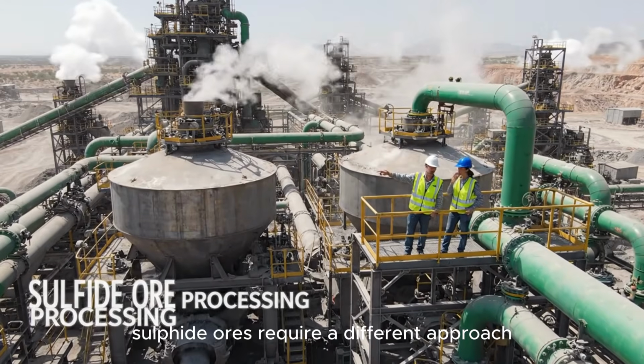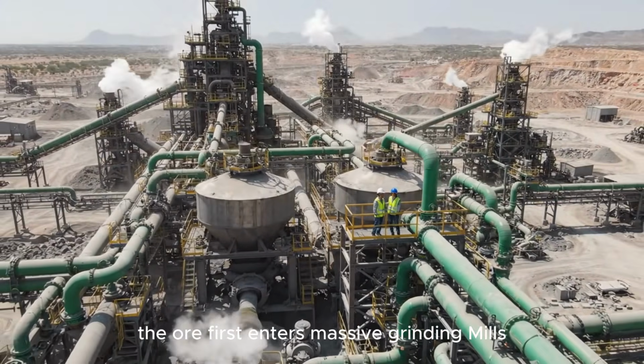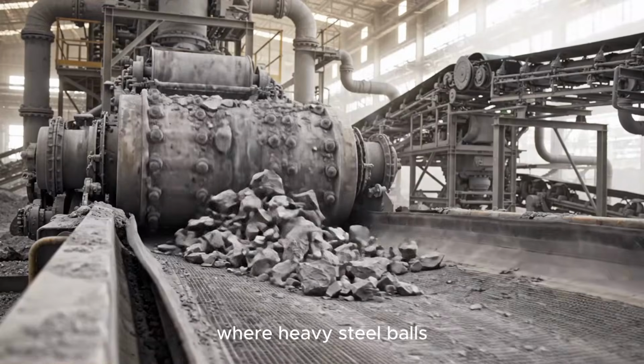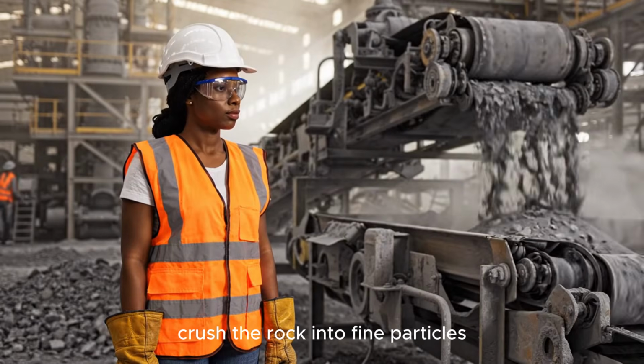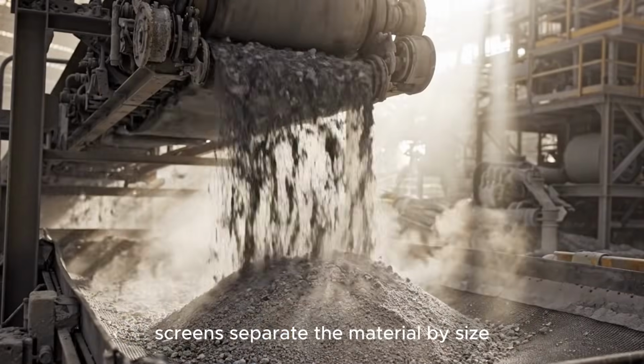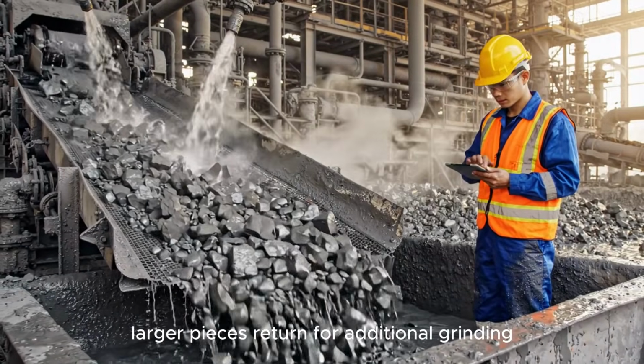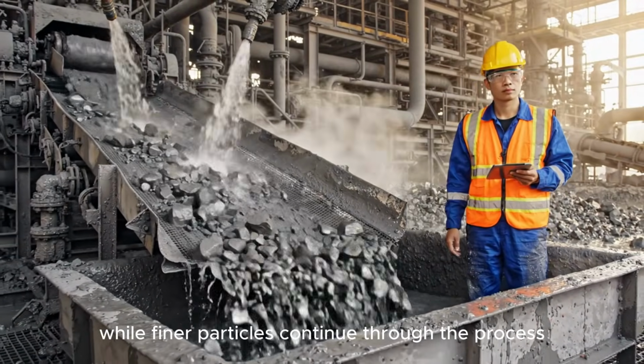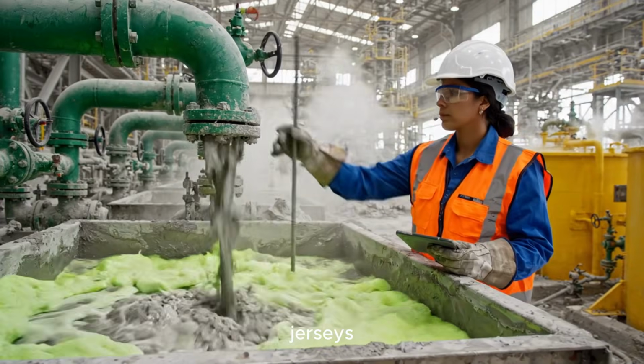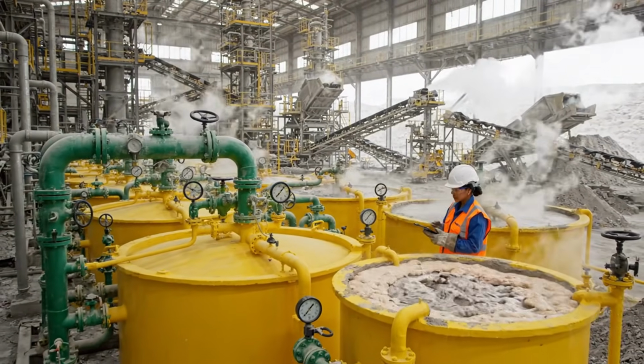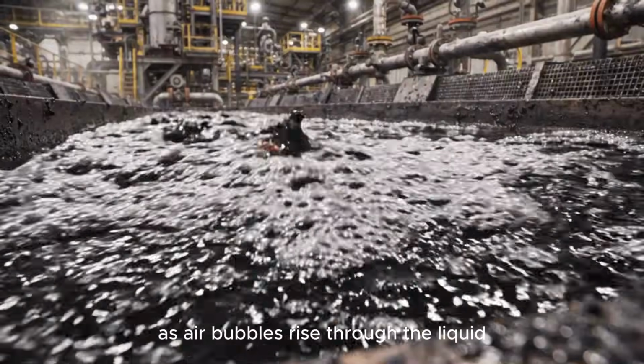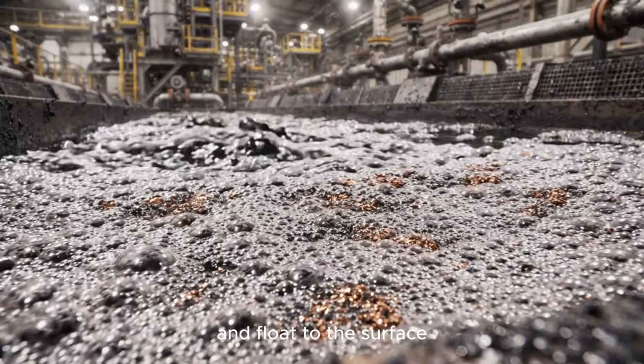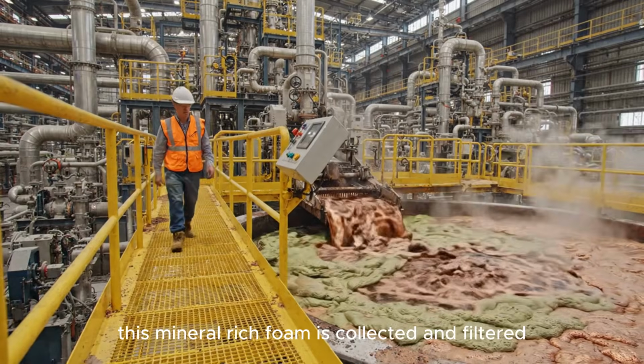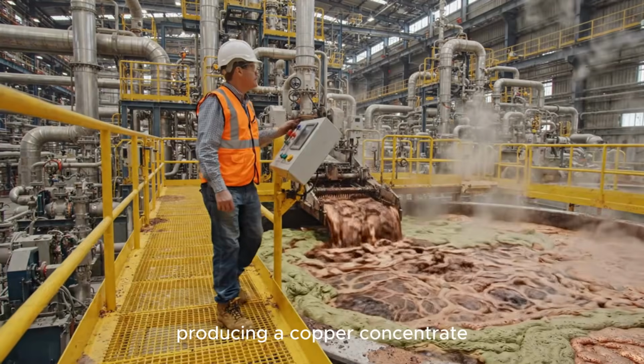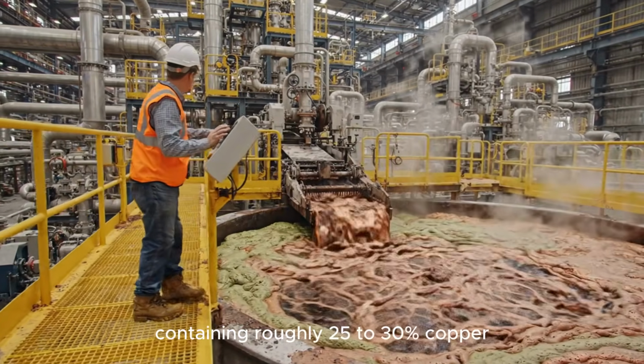Sulfide ores require a different approach. The ore first enters massive grinding mills, where heavy steel balls crush the rock into fine particles. Screens separate the material by size. Larger pieces return for additional grinding, while finer particles continue through the process. Special chemicals are then added to make copper particles repel water. As air bubbles rise through the liquid, copper particles attach to them and float to the surface. This mineral-rich foam is collected and filtered, producing a copper concentrate containing roughly 25 to 30% copper.